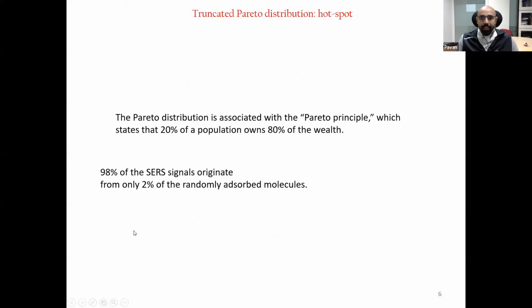It tells you that this particular enhancement factor follows something called a Pareto distribution, which you probably would be aware of in the context of economics, where, for example, 20% of the population owns 80% of the wealth in a particular country. Now, in surface enhanced Raman scattering, the same Pareto distribution comes into the picture, where 98% of the SERS signal essentially originates from only 2% of the randomly adsorbed molecules in the hotspot. So no matter how many molecules you have in your experiment, what really facilitates the enhancement is only those molecules which are present in the hotspot. So only 2% of those molecules really are contributing to almost 98% of the SERS signal.